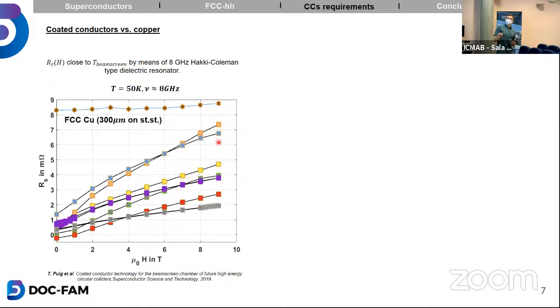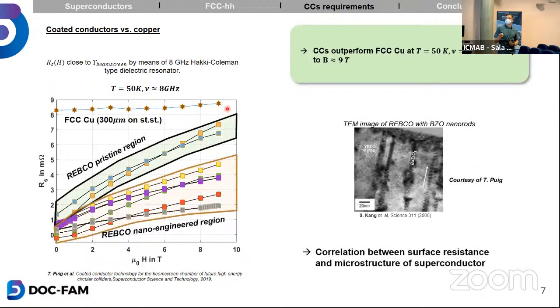But we see that up to 9 Tesla and 8 gigahertz, the coated conductors perform better than copper. So good news: superconductors are preferred in this case. The second thing, again, we see a link between the microstructure and the performance of superconductors. If you introduce, for example, pinning centers like BZO nanorods, nanoparticles, or you even try to incline the c-axis of your superconductors, the performance in field becomes better. So again, a clear correlation between the surface resistance, or even surface impedance, and the microstructure of the superconductor. I want to mention that we measured it at higher frequencies than actually necessary for the FCC. The FCC would only have mirror currents up to 1 gigahertz.